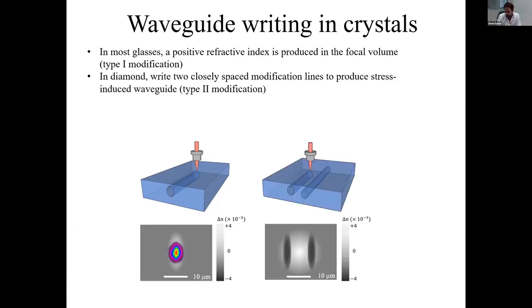Now in crystals, unfortunately, as you absorb the light within the crystalline lattice, you're modifying the crystal. You're taking this nice periodic arrangement of atoms within the crystal lattice and essentially modifying them. You're causing amorphization, which results in a decrease in density. And this decreased density results in a depression of the refractive index. So this is not ideal for forming an optical waveguide with one shot.